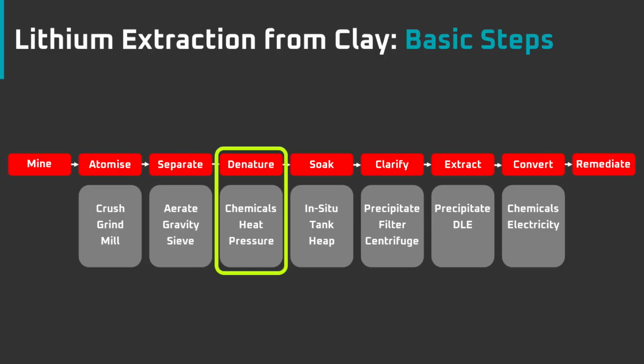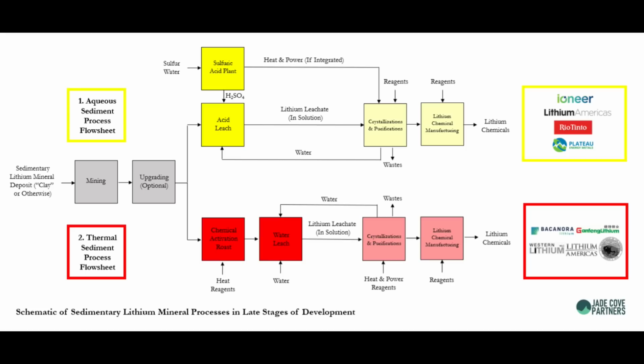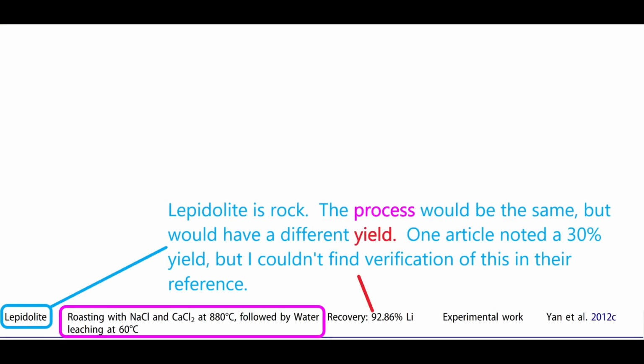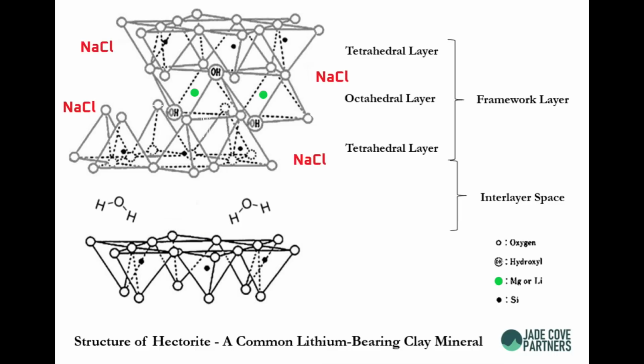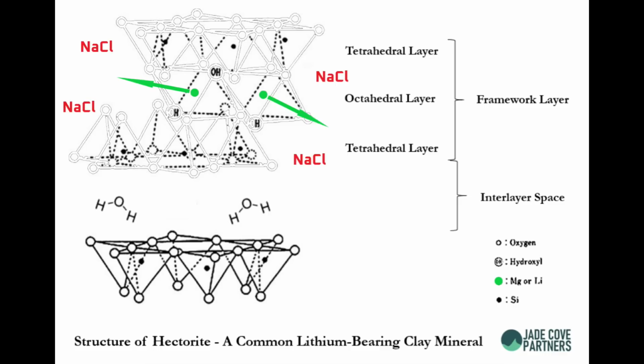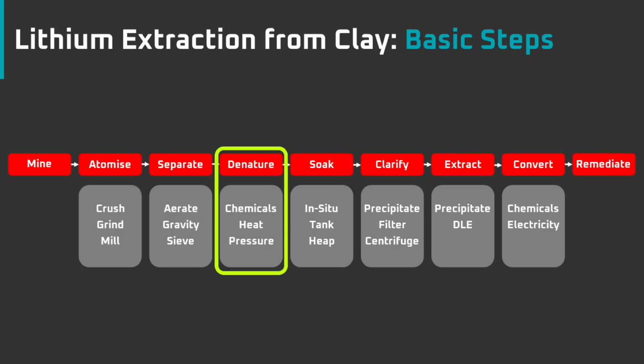Next, the denaturing stage. By denaturing, I mean breaking down the crystal structure of the lithium clay. This is typically done with heat or acid to release the lithium, but Tesla said they would use an acid-free process. An alternative to acid and heat is to denature the clay with table salt and heat. The clay plus salt mixture would be roasted at a temperature of around 1000 Celsius, where the salt would become highly reactive and denature the clay, releasing the lithium from the framework layer. Salt costs about $60 per ton, so it's extremely cheap. Although the energy cost would be high, Tesla is an energy company and might be able to generate this electricity at very low cost.